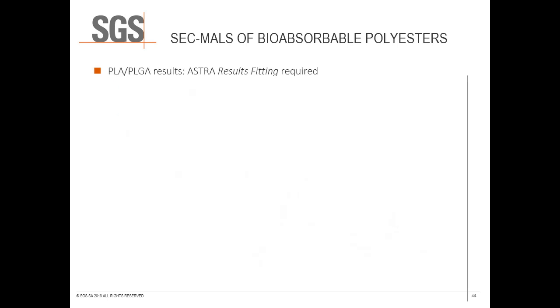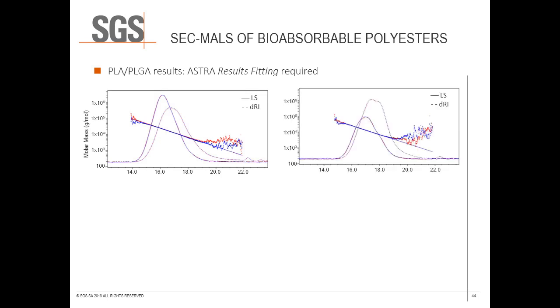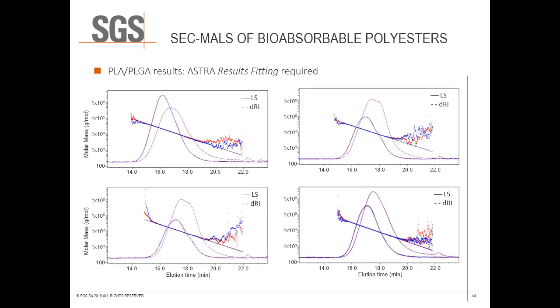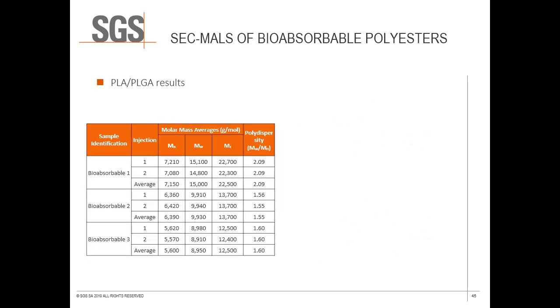The results fitting procedure was applied consistently across all experiment injections, as shown in this sampling of chromatograms and molar mass plots. Note that the bottom right figure actually contains 4 separate injections: duplicate injections of a sample preparation at the beginning of the batch, and duplicate injections of the same sample preparation at the end of the batch, as a measure of instrument and analytical consistency. The non-Gaussian peak shape here is not due to viscous fingering, as evidenced by the reproducibility between replicate injections, but is representative of the polymer chain size distribution. The numerical results confirmed the information we had been given regarding the molar mass range of the samples.